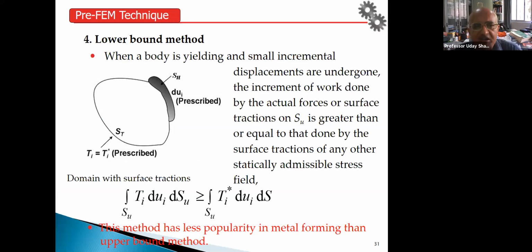Similar to the upper bound method, in fact, the lower bound method is also there. In this, you don't assume any velocity field, but you assume a type of stress field. So in this, when the body is yielding and you consider that plastic deformation is taking place, based on a hypothetical stress field, then you calculate the power, etc. Then this power will be less than the actual power. So if you do both upper bound and lower bound analysis, you can get an estimate of this. But these techniques, of course, have many limitations, because here you are talking about only finding out the power, but you are interested in finding out many other things.